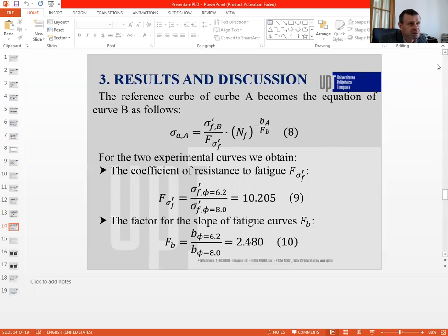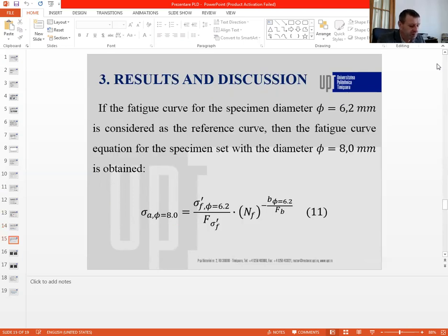The coefficient of resistance to fatigue is, equation 10.205, and the factor of the slope of the fatigue curves, FB, equation 2.480. If the fatigue curve for the specimen of diameter 6.2 is considered as the reference curve, then the fatigue curve equation for the specimen set with diameter 8.0 is obtained, equation 11.